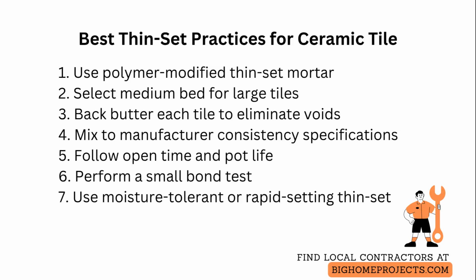Always perform a bond test by troweling a small area and checking for full coverage after bedding a tile, then removing it to inspect the mortar transfer. For substrates with moisture or contaminants, use a moisture-tolerant or rapid-setting thin-set and consider a cementitious primer or slurry bond coat if the manufacturer recommends one.